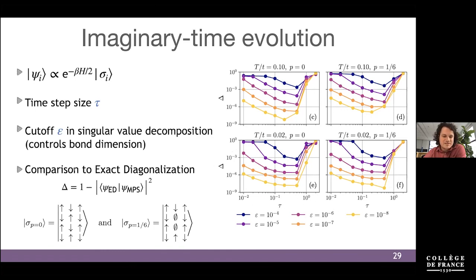And what's shown on the y-axis is this defect delta, which is 1 minus the overlap of the MPS time-evolved state with the state from exact diagonalization. So we have this control parameter tau here and this control parameter epsilon, which are the different colors. And we see something remarkable. If we decrease the cutoff, we get very accurate results. This defect is, for this parameter for example, accurate up to 8 digits, and I think this is rather remarkable precision.